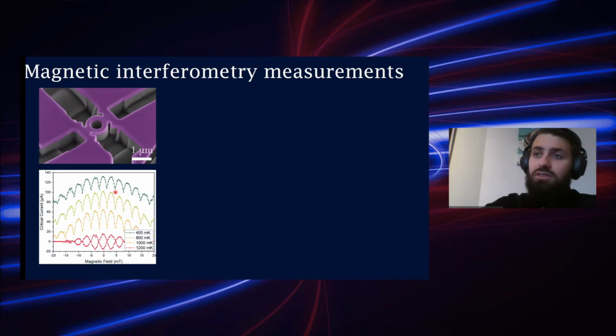What we found is that the critical current is strongly dependent on the magnetic field that threads the ring.